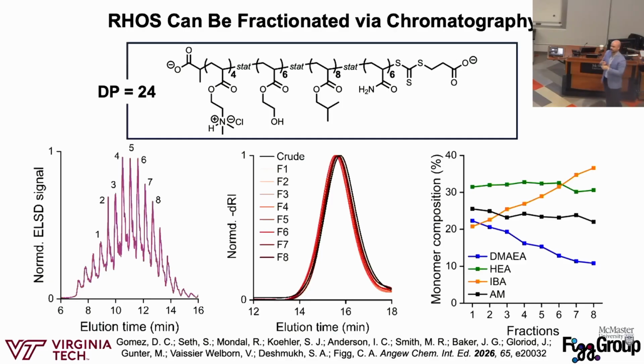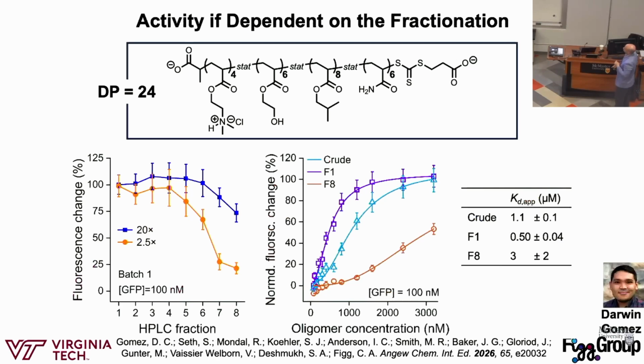We're just doing affinity chromatography with a hydrophobic column, so the hydrophobic things will elute later than the less hydrophobic things. Fraction 1 has about the same amount of cationic charge and hydrophobicity. Then as the fractions go on, the hydrophobicity increases and the cationic nature decreases, whereas the other two monomers stay about the same. And now if we do assays with these fractions from the polymerization, we actually see differences in functionality even with those fractions.